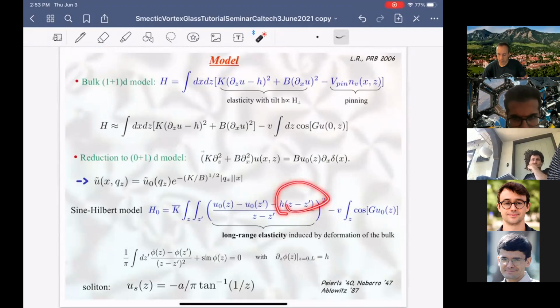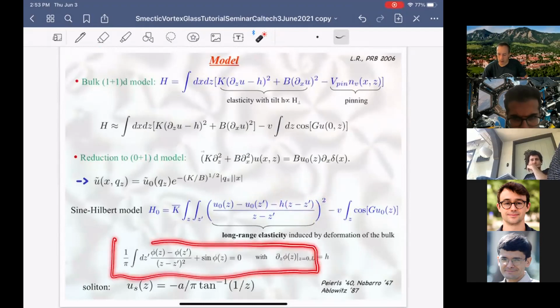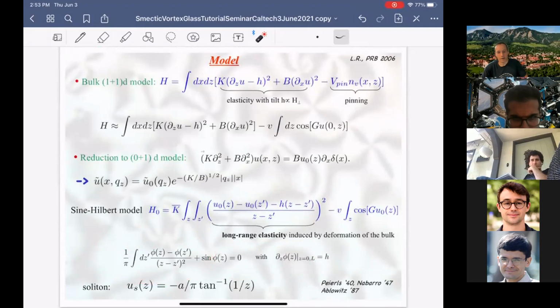And here's the tilting. Here's the corresponding Euler-Lagrange equation, which is the Sine-Hilbert equation. This is a Sine-Hilbert transform of the elasticity. Amazingly, although I went and solved this problem to the extent that I needed myself, it turns out that there are nonlinear solutions to this equation, soliton solutions, and here's the basic one that goes back to Peierls and Nabarro in the 40s, and then was actually fully explored as an integrable model by Ablowitz using inverse scattering methods in the mid 80s.